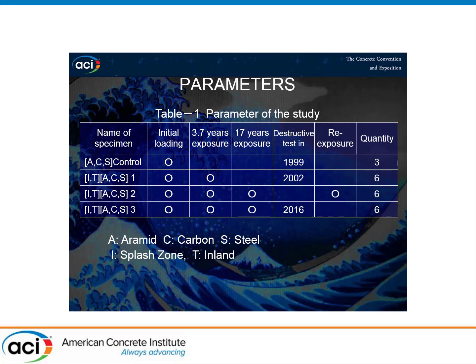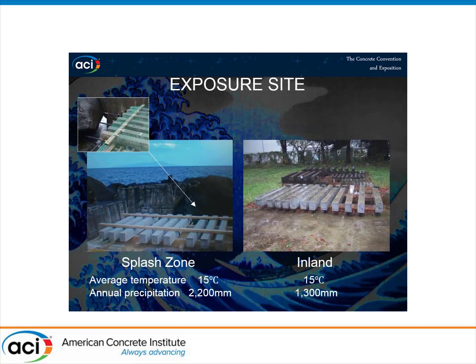Control is a non-exposure and destroyed at its age of 2 months before exposure. Number 1 destroyed at age of 3.7 years. Number 3 is destroyed at age of 17 years. And number 2 is still in exposure. This photo shows exposure site. Left, the splash zone. There is a hole in the rock through to outer sea, and when the weather is bad, spray blows to specimens hardly. Very severe environment. And right, inland, in ordinary environment, no salt and no heavy precipitation.